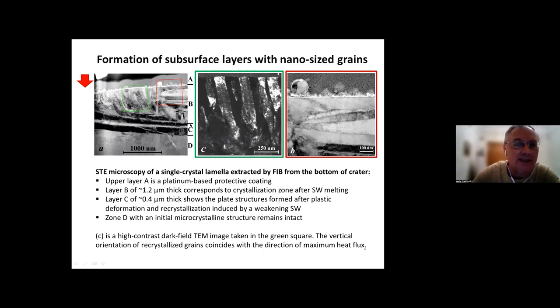Below this layer, we see layer C, also a modified layer. However, because of attenuation of the shock, the amplitude of the shock was not enough at this depth, and melting does not happen. Instead, the elastic-plastic transformation still continues, and recrystallization resulting in the formation of a new microcrystalline structure may happen here. Below, in zone D, the material stays intact with its initial crystalline structure.